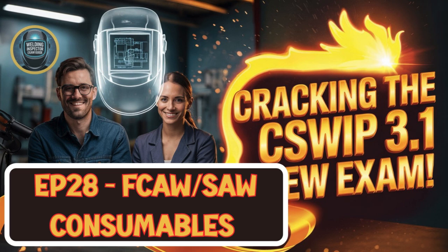An FCAW wire is essentially a metallic sheath. Think of it like a thin, continuous metal tube that's filled with a powdered core. The metallic sheath, the outer tube, has two main jobs. It provides form stability to the wire so it can be fed smoothly through the welding torch without collapsing. And it serves as the current transfer medium during welding, carrying the electricity down to the arc. But the real magic, as you said, the powerhouse, is that filling powder inside the core. This powder is a true multifunctional marvel. It does several things simultaneously.